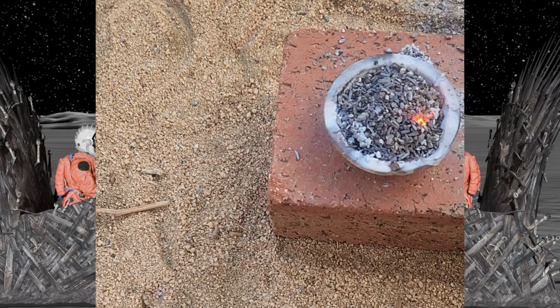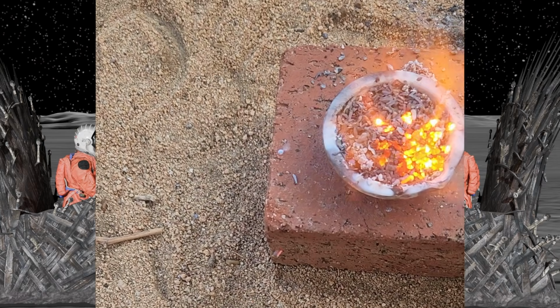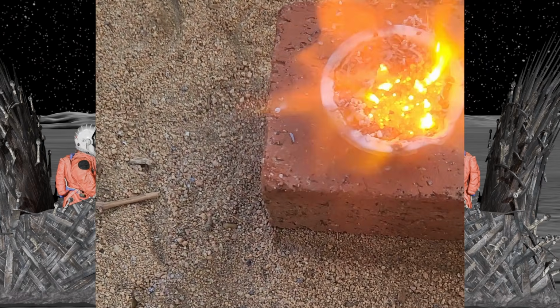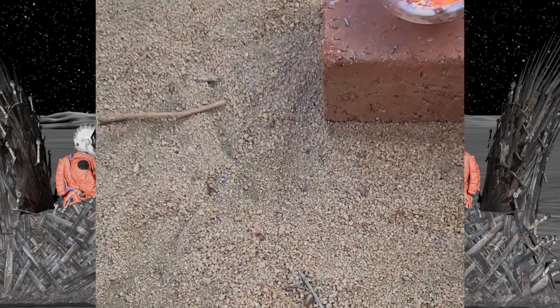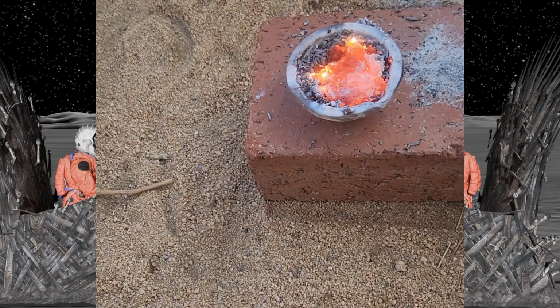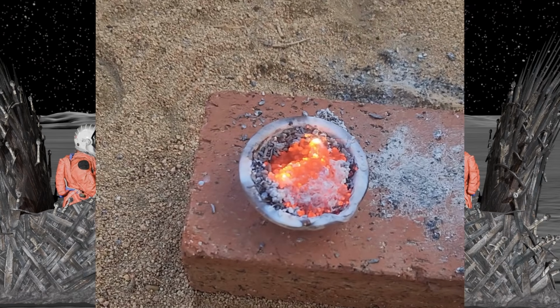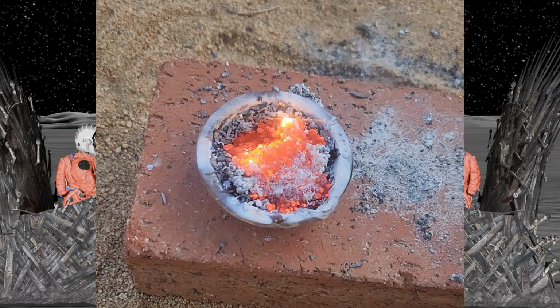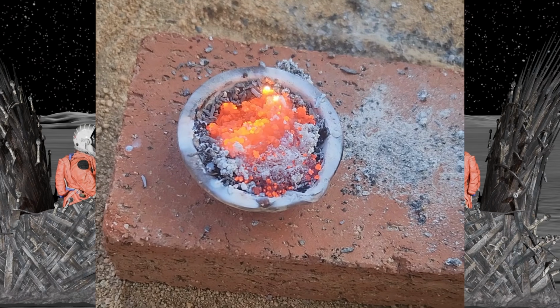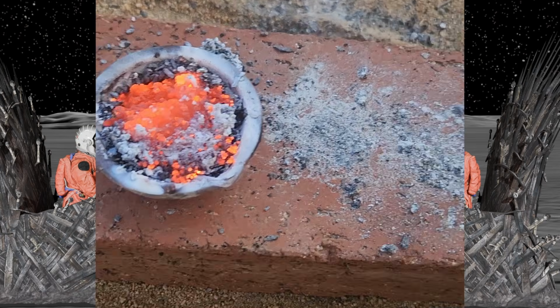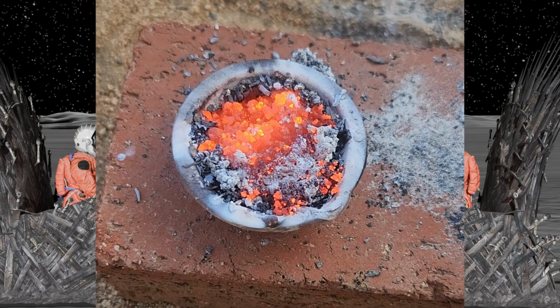Basically almost a thermite reaction. It is a thermite reaction with lunar simulant. And it's exothermic in nature, so it gets up to pretty extreme temperatures, which serves almost, if you're going to do pyrolysis on the slag later, like a preheating step in a lot of ways. You might even get some sublimation from this step alone, which could actually be a problem if you're trying to recover everything, but I'm sure it's manageable.